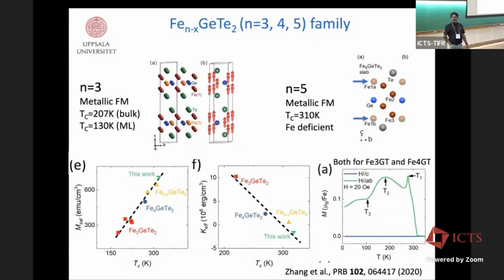So how is that affecting this exchange interaction and the spins at each ion? Here we have explicitly replaced iron by cobalt and nickel, so this is not really a gating effect. That changes the exchange interaction parameters, definitely. Iron-iron exchange interaction is the most common, but when you dope with nickel or cobalt, you have iron-nickel, cobalt-iron, nickel-nickel, and so on, three different exchange interactions. So definitely iron-iron exchange interactions are getting modified in the presence of nickel or cobalt, for sure. Thanks for this very nice talk.